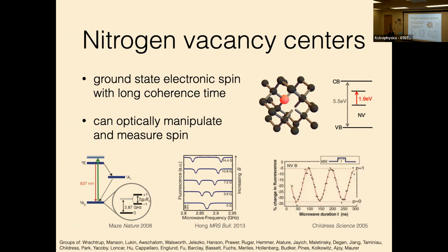So to first order, you can really think of these as molecular orbitals. You don't really have to consider the extended lattice at all. And it turns out that the NV center is a spin 1 defect that has extremely long coherence times, even at room temperature. The coherence times are really limited by a spin lattice relaxation that's about 7 milliseconds. And this is really unprecedented. There's essentially nothing else in the solid state that has such long spin coherence times, including other atomic defects.